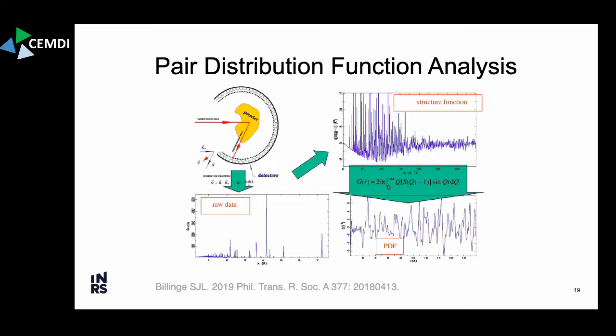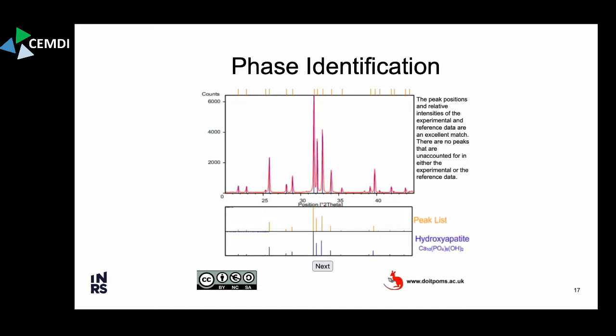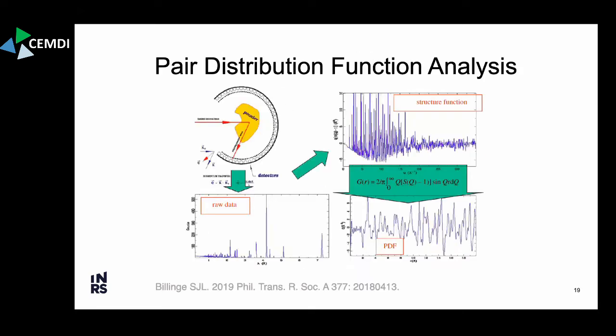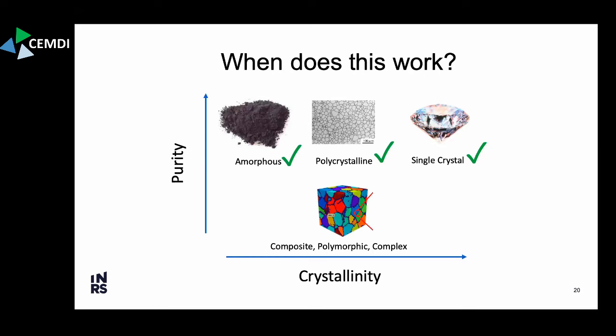So in pair distribution function analysis, you have a problem where you don't have well-defined peaks in the diffraction pattern. From an amorphous material, what you get is a very smooth, broad, continuous signal, basically. But you can still treat this signal with some mathematics and take the Fourier transform, and you're left with the pair distribution function. This is just the conjugate of the measured intensity. And so each peak in the pair distribution function, you can use in order to measure, this is actually your sort of bond lengths within. And so then you can get local structural information. So this is useful. You can characterize the local structure of amorphous materials.